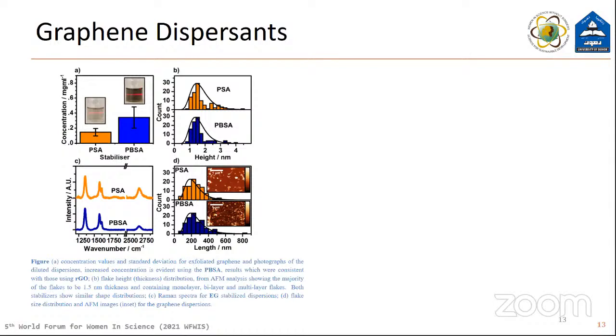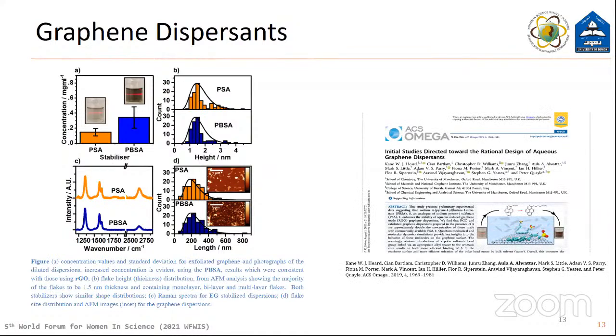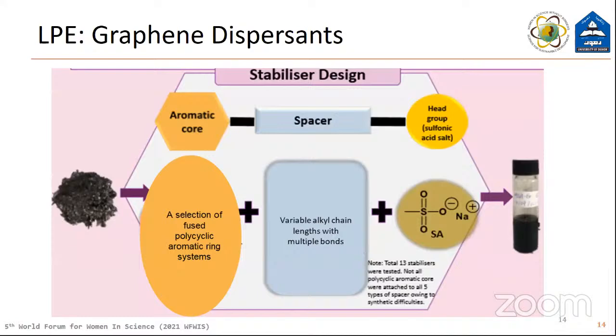Having shown that a simple structure change can have an observable effect on stabilizer efficiency, and that these effects can be rationalized using computational methods, this allows development of a rational approach to stabilizer design and mapping of the exfoliant once bound to the graphene or reduced graphene oxide surface. And this was published work in the ACS Omega journal. So our result was promising and encouraged us to do more design and development.